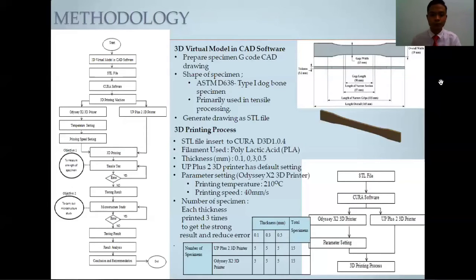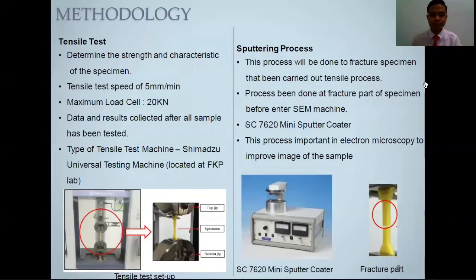Okay, now we proceed to the tensile test. The tensile test purpose is to determine the strength and characteristics of the part or specimen produced. The tensile test was carried out with 5 mm per minute speed, and the maximum load cell the machine can achieve is 20 kN. The tensile test machine used is a Shimadzu Universal Testing Machine, and this machine is located at the FKP Lab. The figure below on my slide shows how we will set up the specimen at the tensile test machine. Then we will proceed to the sputtering process.